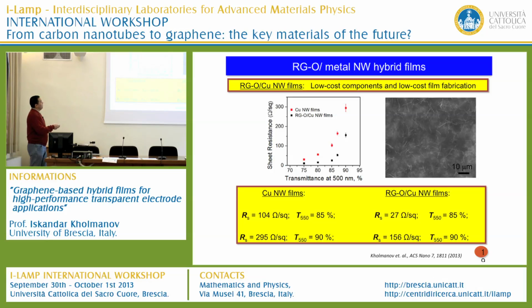This is the SEM image of the reduced graphene oxide copper nanowire film. And this is the sheet resistance versus optical transmittance. The red dots show only the pure copper nanowire film. You see the sheet resistance of the copper nanowires is higher than the hybrid film, copper nanowire coated with RGO film. In this way, we significantly decreased the copper nanowire film sheet resistance that initially was about 100 ohm per square. After assembling with RGO, we obtained about 27 ohm per square sheet resistance.